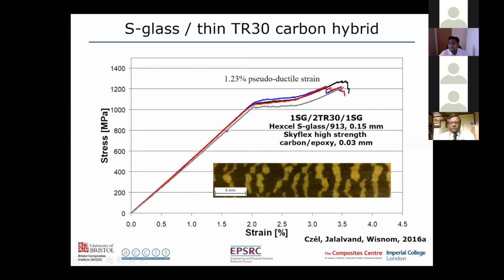Another interesting aspect of this is this pattern that we see on the surface. So the laminate is initially black due to the carbon, but when it fragments and we get delamination, then you see these patches appearing because the light doesn't get past the interface between the glass and the carbon. So this is a very nice way of visually demonstrating that we've exceeded the pseudo-ductile yield point, and is very promising as a way of indicating an overload.